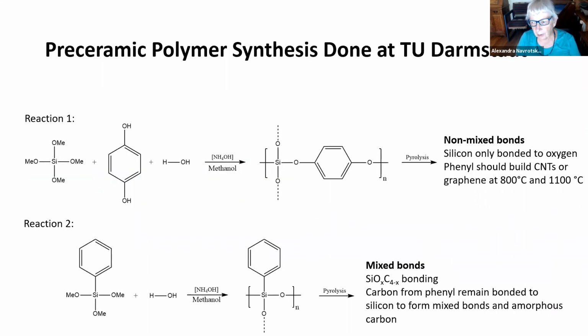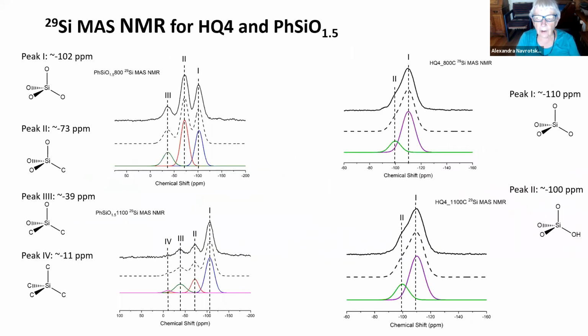This is the pre-ceramic polymer synthesis route for those of you who like drawing organic molecules. And this is the NMR spectra of two of these samples, so one with and one without a bunch of mixed bonds, and one sees the difference very clearly.